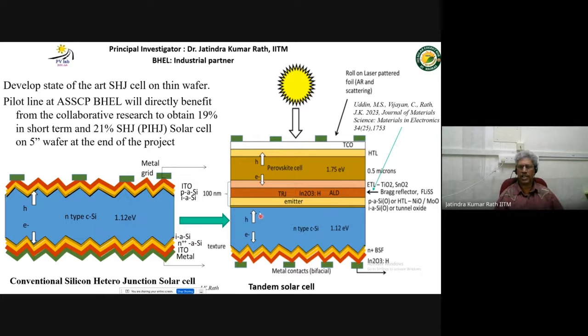But if there are no textures here, its absorption becomes less. So what we do here, we put a topographically flat, optically rough surface, with 2D photonic structures here, and with the back reflector we put it here, so that we manage this light in such a way that scattering goes up inside here and a lot of light will be absorbed. This was published recently, how to make this one.